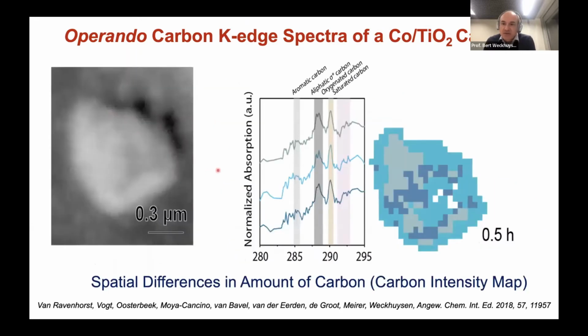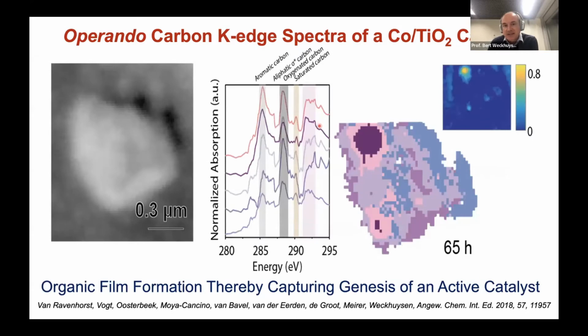When I focus now on, for example, 0.5 hours in the carbon map, you can see that you have different features. Important is to see here that this aromatic one is low in intensity, and here you see oxygenated, which actually you can also see in the reactor first, and then you also have aliphatic, what you expect. And when time develops, you see this aromatic developing further. I don't have now the time to discuss that, but these are indeed precursors which are put on the surface and are these carbon deposits which are likely formed during the catalysis. So this brings me